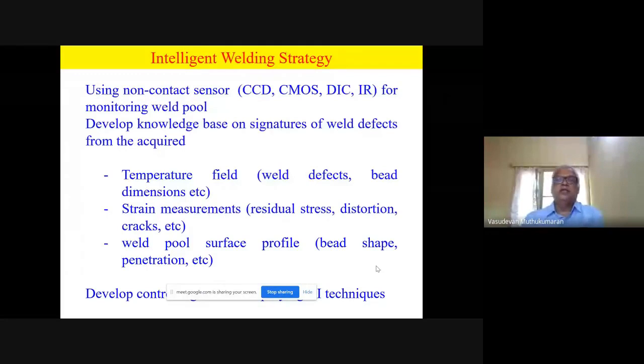I will show you some of the signatures we captured using the IR camera. The temperature field we can measure can be correlated with weld defects and weld dimensions. And using the CCD camera, we can use strain measurement that can be correlated with residual stress and distortion or crack-like defects. Then the weld surface profile we can capture using this camera can be correlated with the bead shape and penetration. So first we have to develop a database, a knowledge base, on the various defects and the weld dimensions correlation with the image profiles.